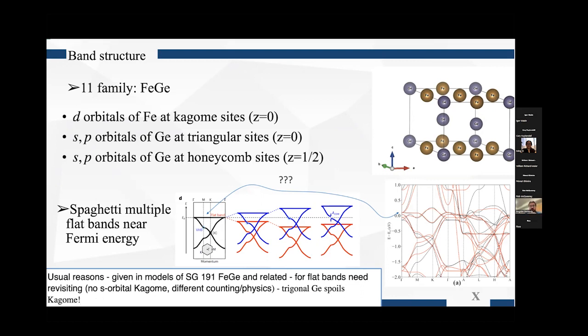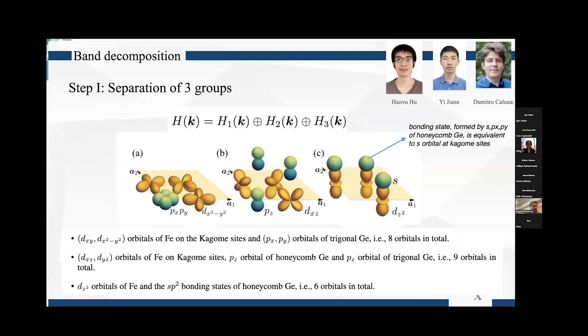Well, first of all, what we do is a separation of orbitals that's basically half based on symmetry, half based on chemistry. So it's not an exact symmetry because the orbitals shouldn't be separated by mirror at finite momentum, but it's good enough, as we saw, because it fits the data. So what we see is that you can, at first order, separate the Hamiltonians into 3 groups. The first group is made by the in-plane orbitals, pxy and dx²−y², dxy. The second group is made by dxz and dyz orbitals, and the third group is made by dz², and some combinations of them with germanium orbitals in this case, for example.